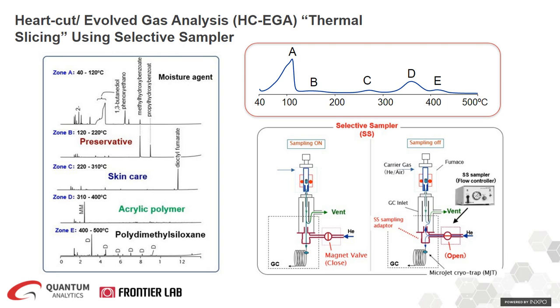So there are zone A, B, C, D, and E. So heart cutting allows you to slice your EGA thermogram into smaller temperature zones, such that you program your furnace for zone A from 40 to 120, zone B 120 to 220, all the way to zone E, and you obtain a separate GCMS chromatograph run for each zone.